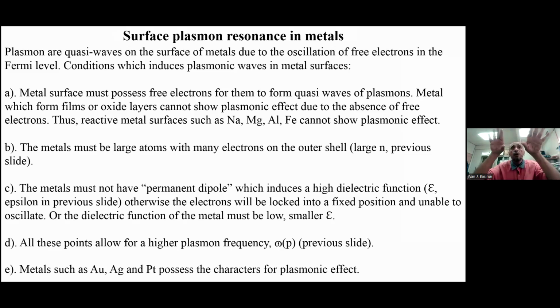But not all metals can actually give you this effect. For example, if the metal is reactive, like sodium, when you expose sodium to air, you get sodium oxide. Aluminium, when it absorbs water moisture, becomes a film. When you have an oxide layer or film formation on the metal surface, the electrons are fixed in position, meaning the electrons cannot vibrate freely. That is why reactive metal surfaces, like sodium, magnesium, aluminium, iron, calcium, which can bond with oxygen in the air or water moisture, cannot show plasmonic vibration or plasmonic wave.